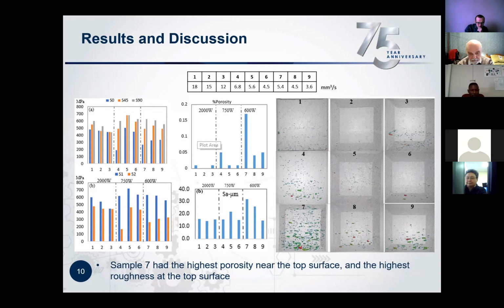Sample 7 had the highest porosity when we did the measurements. You can even see it on the images, the worst one. And then of course, when we looked at the surface roughness as well, it was also the highest. There's some kind of a correlation there. So the rougher the surface of your layer, you must expect to have more porosity in your surface.